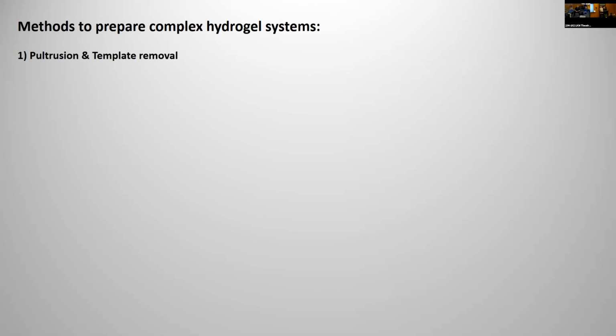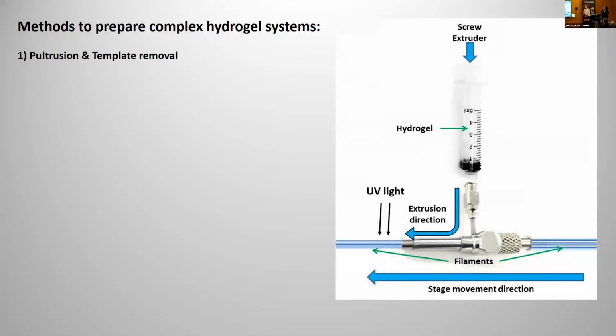So the first one is using a pultrusion technique, which in industry is, if you sort of think of it as the opposite of extrusion, where instead of pushing stuff out, you are pulling a printing technique platform along some reinforcing fibers. So usually you'll use this to embed fibers within a plastic or material that you want to reinforce. But what I've done is then pulled those fibers out to leave hollow channels through the material. So I'll show you what I mean.